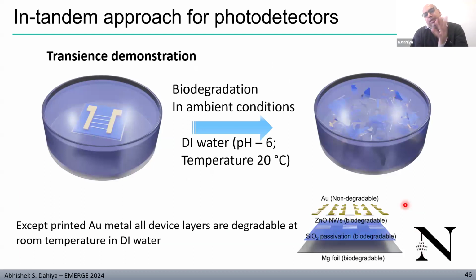And then we tested its degradation at around pH 6 and a temperature of 20 degrees Celsius, and we see how these layers start to disintegrate and degrade with time.